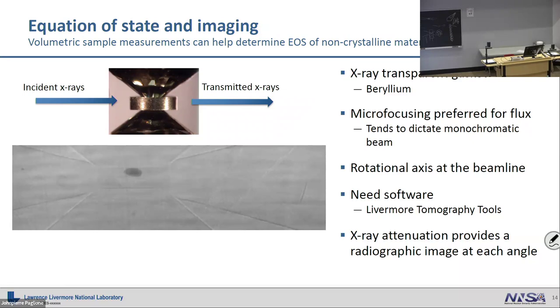In this case, the reason we use beryllium is because we're going to shoot X-rays through the side here. That's the nice part about the periodic table. It's up there, right? So if diamond doesn't absorb your X-rays, then beryllium won't, because it's lower Z. And diamond's actually pretty high density. Beryllium is basically a metal in terms of its crystal structure, it just doesn't have any electrons at the Fermi level. So beryllium scatters very little. You come in here with 20 kilovolts and you'll never see the beryllium, it's basically invisible.